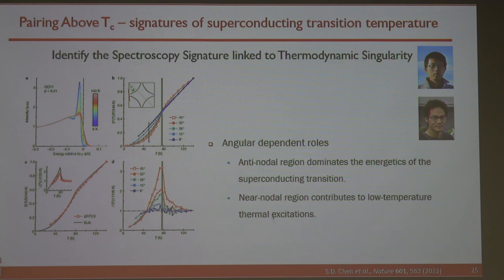Then we have the data, and we can ask ourselves, instead of density of states, because we have many-body interaction, we don't have a single-particle density of states. What if I just use the spectral weight at zero energy as a proxy of density of states? Once I have that, I can calculate the entropy. It's a simple function, just Fermi-Dirac and Boltzmann, and you have density. If you do that, you can get an entropy like this. And if you now take a derivative of that entropy, you see a singularity at the correct TC. Okay?